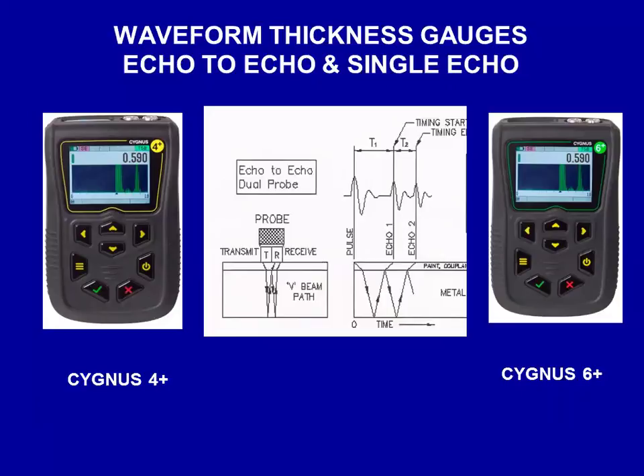You're looking for those relatively parallel surfaces. The repeatability on this is incredible from multiple echoes. You know you got a good measurement when you can hold it there for 5 to 10 seconds or however long. Take it off, put it back on, and you get the same measurement at the same spot. It doesn't make any difference if you turn the probe this way, because you're using a single probe. It's kind of neat to see that.